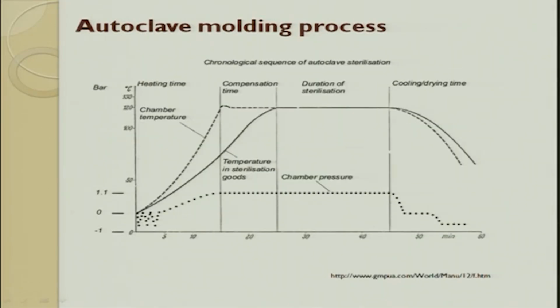So, this is a typical cycle of an autoclave. You can see the pressure maintained in bar, the temperature, and the time in minutes. This is the chamber pressure. We always operate up to 1.1, and you can see the temperature going up. This is the chamber temperature, which has a preheat, then a compensation time, then a duration of sterilization, and then a cooling period. The temperature is held in the sterilization zone.